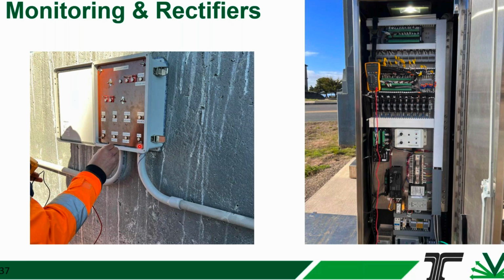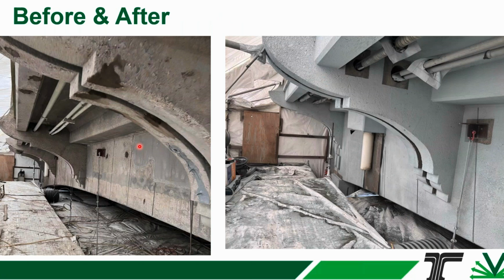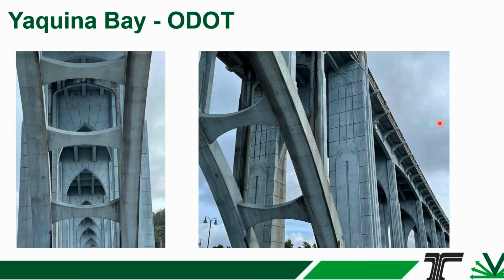Here you've got a picture on the left of the condition of the bridge before this work that was done in 2020. And on the right, you can see the same area after the previous zinc coating's been removed and the new zinc coating has been applied. So it looks fairly nice and uniform. And here you can see a couple of photos of the piers after the reapplication, and you can see there's a kind of grayish color to the applied zinc coating.